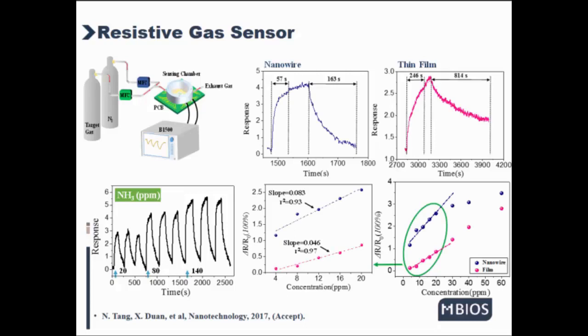And also, a comparison of ammonia detection using a nanowire gas sensor and a thin film gas sensor was carried out here. Due to the high surface to volume ratio, the calculated sensitivity of the nanowire gas sensor is higher than that of the thin film gas sensor. All these results suggest that the resistive gas sensor fabricated by the NAMIC approach has a good gas sensing performance.